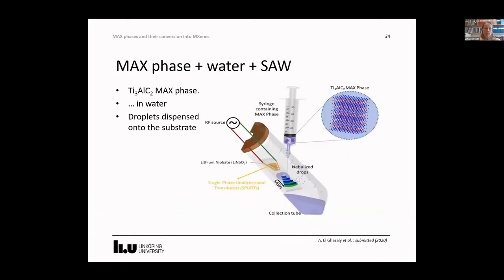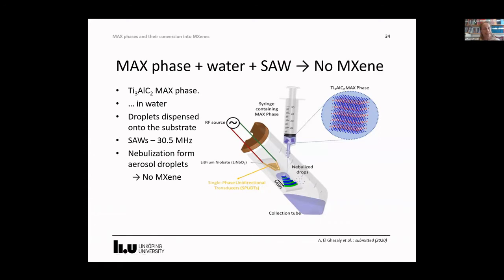Since one can exfoliate moly disulfide and tungsten disulfide, we start by just trying to use the same procedure for a max phase, titanium aluminum carbide. We have inserted the device here into a collection tube, and in here we have max phases in water, and droplets are then dispensed onto the substrate. The surface acoustic waves of a 30 megahertz frequency drive nebulization of the droplet into smaller aerosol droplets that are collected at the bottom of the tube. And if we analyze what we have collected, it is still max phase. In other words, the surface acoustic waves only is not enough to break the interlayer bonding of the max phase.